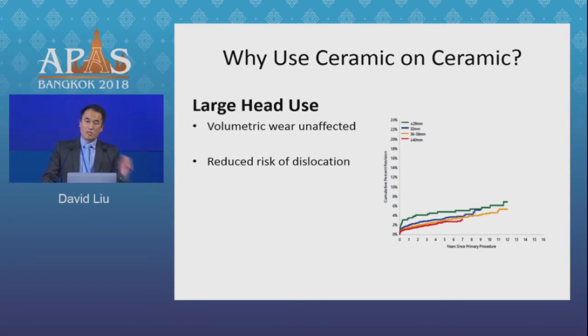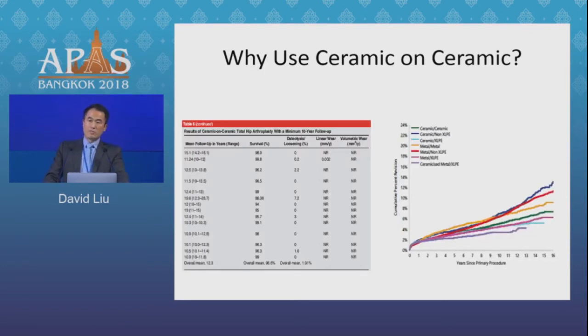Because you get fluid film lubrication, you don't get adhesive wear, so wear of a ceramic articulation should be immune to head size and is not affected by sliding distance. Most registries show that larger heads in ceramic articulations probably do slightly better than smaller heads. There are now midterm studies — 12 to 15-year case series as well as registries — showing that ceramic on ceramic performs well and is a valid option.